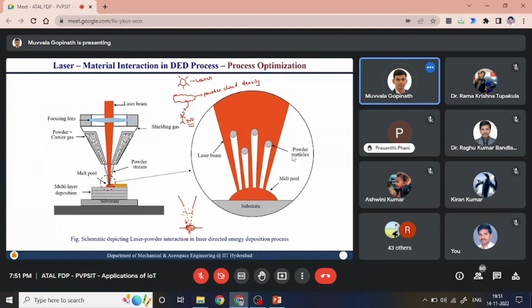Now if you look at this molten pool, whatever initially formed because of the laser light passing through the powder cloud is acting as a trap for the initial powder particles. Once this molten pool is there, whatever solid particle comes gets trapped into this molten pool on the substrate and melts, and due to that melting the molten pool size increases both in width as well as height, trapping more and more powder particles. This is something which happens at the elementary or particle level. One particle after another goes into the molten pool, they melt, they increase the molten pool size, and they keep on building a single track.